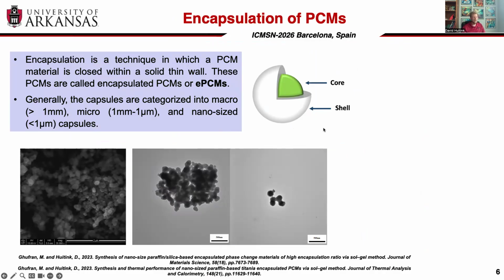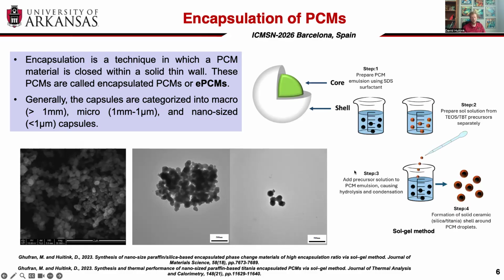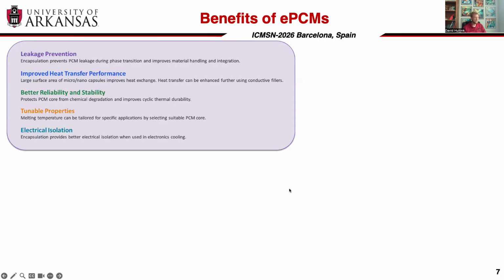And really the novelty of what we've been doing at Arkansas is to deliver submicron size ePCMs that are much smaller than anything that has been produced commercially in the past, but also have some improved properties, as we'll see here in a little bit. And we are producing these here at Arkansas using a sol gel method. So essentially we create an emulsion of the phase change materials and use a sol gel process to encapsulate them with an inorganic shell that basically contains them in this small form factor.